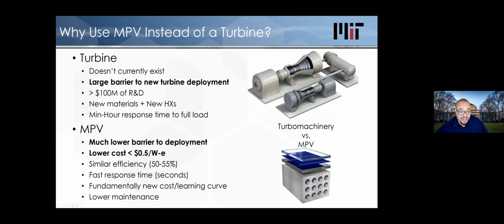We can get to almost the same efficiency range. So I nominally say 50%, but our models actually suggest we can get above 50%, to about 55 or so. We also get the fast response times on the order of seconds, and we can move down the cost curve much faster in this case, right? In the case of turbines, these turbines are well studied, well understood. We know how low their costs could eventually get, and it's not sufficiently low to compete with photovoltaics. However, with PV, if you come up with better PV cells after 10 years, you could go in and replace them. And also they may have lower maintenance.